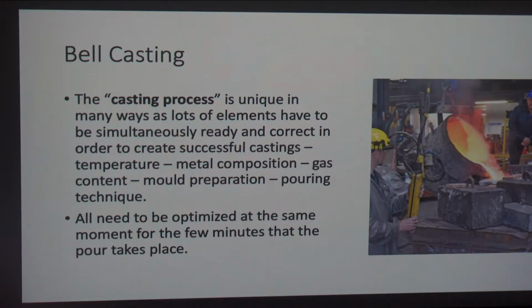You should have a gas content as little as possible, because molten metals absorb gas, and particularly copper-based alloys. Copper can dissolve 7 times its own volume of hydrogen, which is pretty shocking, how easily the metal can become gassed. And then, of course, the pouring technique itself. But all of this has to be optimized for those few minutes when the pour actually takes place. So there's quite a lot you've got to go into to make it all come together.